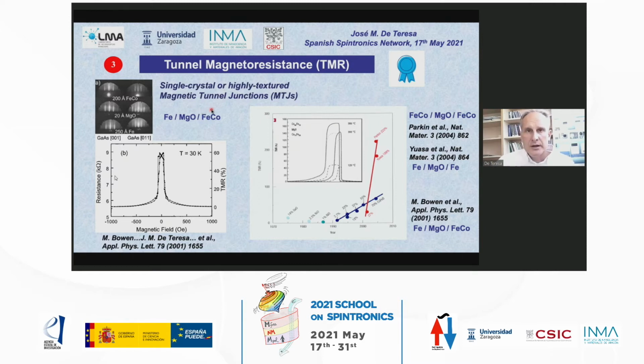And then there were other groups with very good growth machines who also grew these samples. These were the groups of Parkin and the groups of Yuasa, and they observed a very, very large magnetoresistance effect. So from our point here, 27% at room temperature, they were able to achieve more than 200% magnetoresistance. And then the topic exploded, and people started to investigate tunnel junctions based on magnesium oxide insulating barriers.